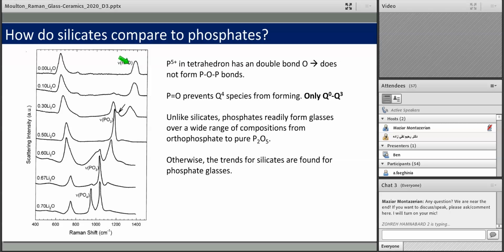It's quite strongly bound, so that shifts it to higher frequencies. And otherwise, you have the Q3 band somewhere under here, a Q2 band comes in, Q1 and Q0 forming.